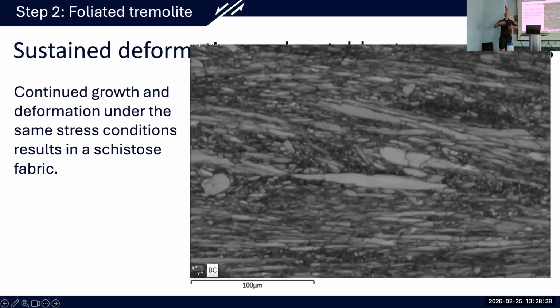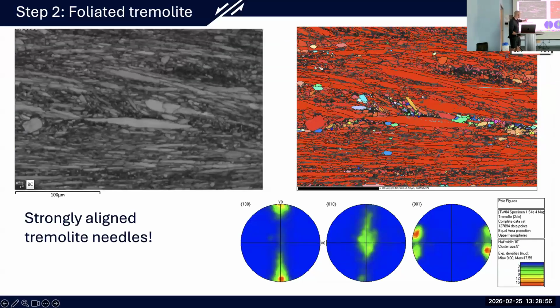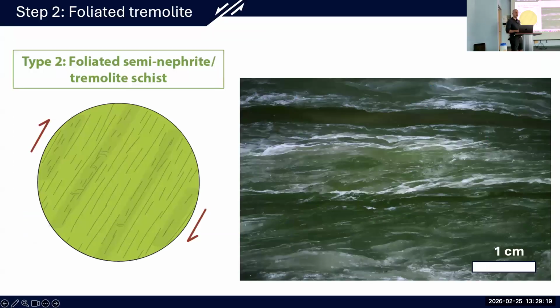However, it's worth noting that within these shear zones, the actual organization of stress is incredibly complex. And we might be looking at a single rock that's the size of your hand, but stresses evolve over time within a larger region, and they do so in a complex pattern. And so even though this results in a very strong alignment, it might only be in a small pocket. And that stress field is liable to change. So despite this resulting in that super strong alignment of needles that we see here, that might not be the case if we continue to deform. And that's our next step.